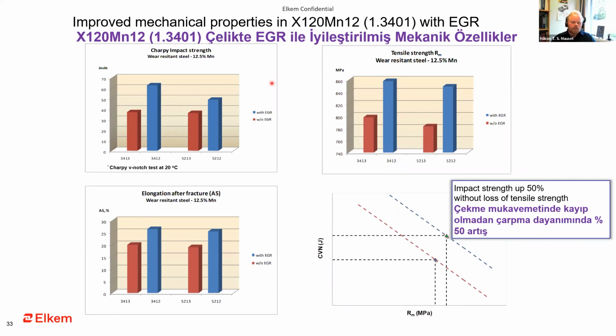Then we can look a bit at a 12% manganese steel with EGR. For this one, we see what we have seen earlier, the Charpy impact strength at 20 degrees C. Typically around 35 joules without EGR, but then up at 60 joules with EGR. And we see sort of the same here, a bit lower here with EGR.